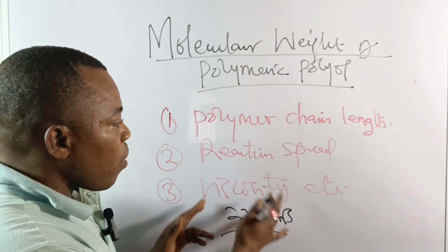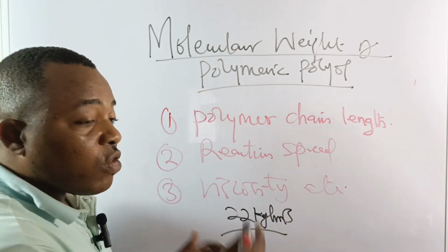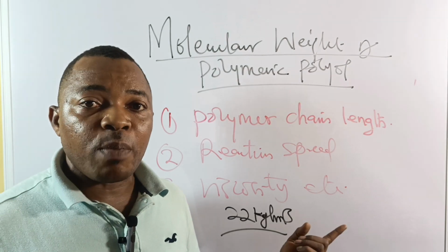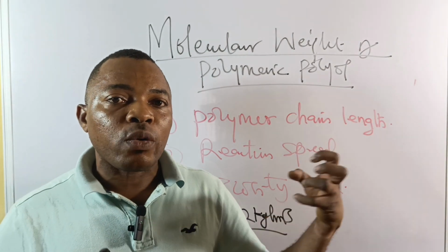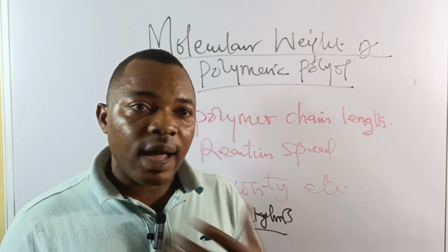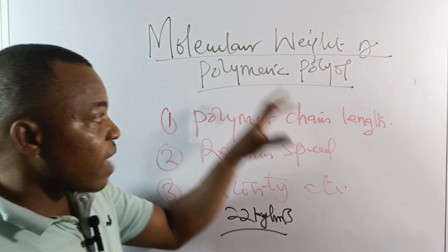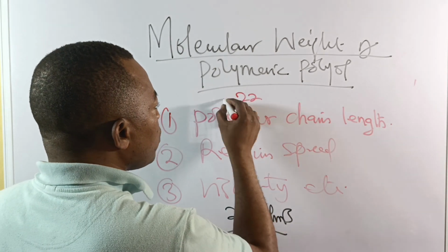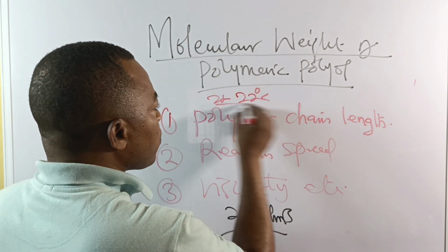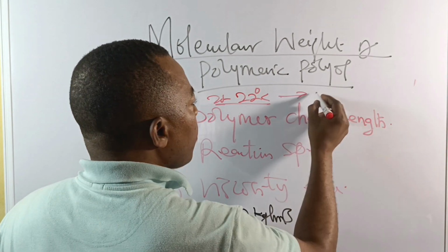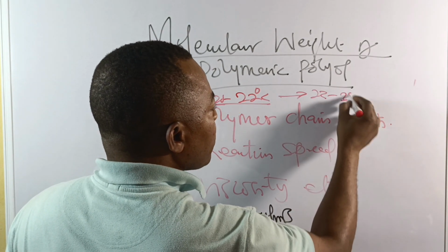Now, in terms of viscosity, I think I've mentioned it. The viscosity buildup is going to increase. And for such polyol with high molecular weight, I advise people not to chill it to a certain level. If the standard cooling system is 20 to 22 degrees Celsius of temperature control, you can take this one up to 23 to 25.